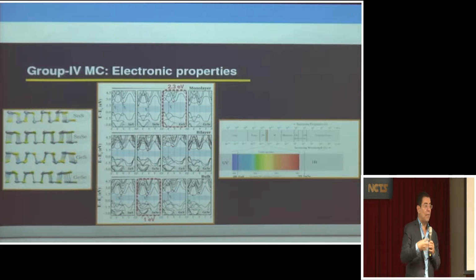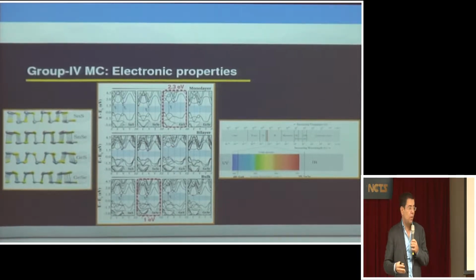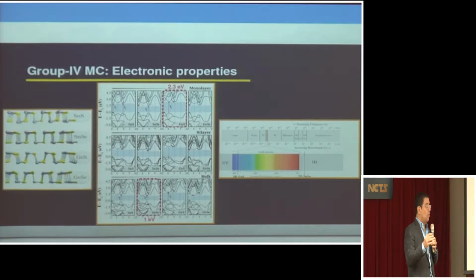So this is why these materials are so interesting. And of course, you can calculate, for instance here, this one in the gap, it turns out that it changes with the number of layers. So if you put more layers or less layers, you can also control the size of the gap. So the band structure can be engineered in many different ways, either by choosing the material or by stacking the material in the right way.